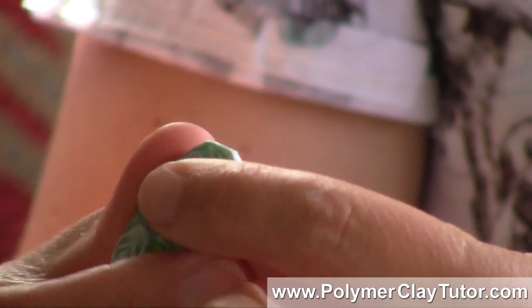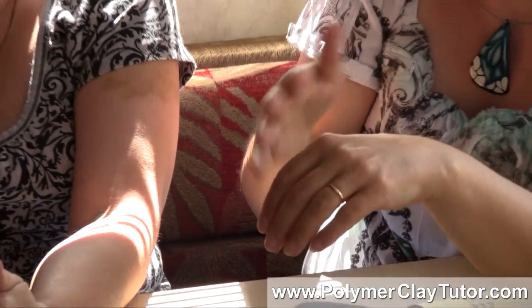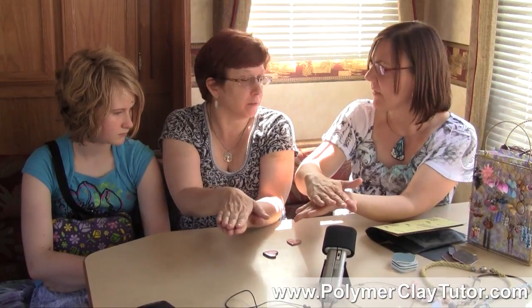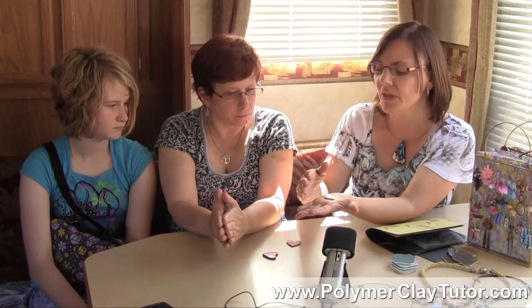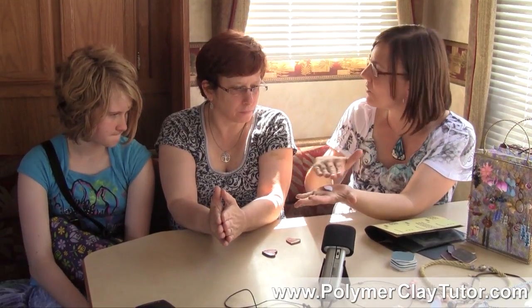When you're doing layers like this — if you're just going to do a flat layer, one layer only, and you are worried about bumps — what you do is take your piece and turn it upside down when you bake it. Because then any bubbles that are on there are going to rise up. What I like to do is have a ceramic tile, a piece of paper or card stock, lay my piece on top of that, put another piece of card stock on top, and lay a tile on top — that'll force it to flatten out. You're baking for a whole hour, right? Good. It takes a little more time for the heat to get inside, so you'd never want to do a really short bake. That should help keep the bubbles at bay and keep it smoother on the back.